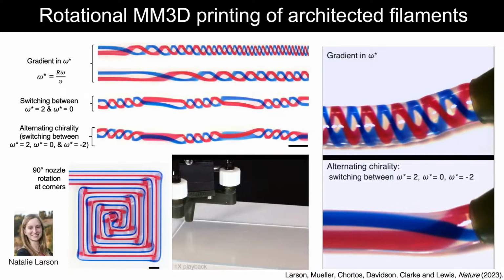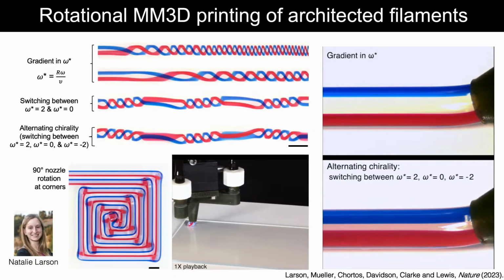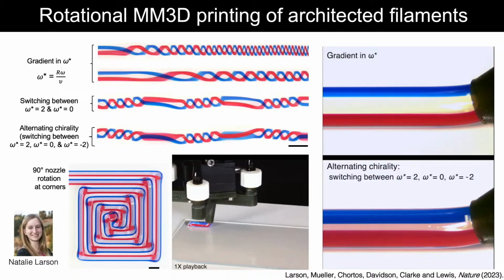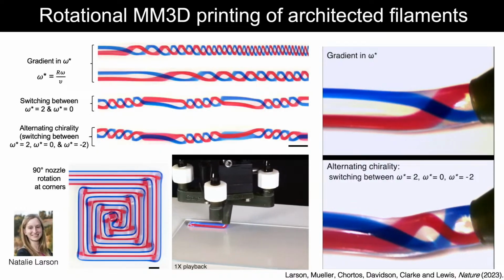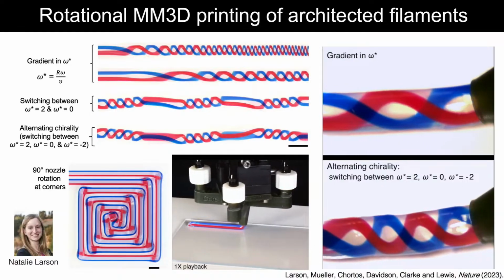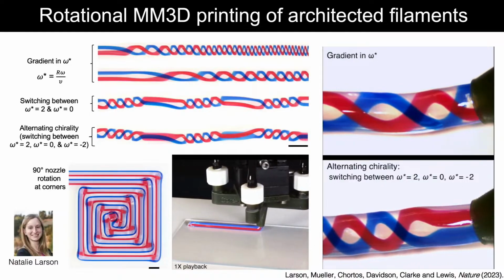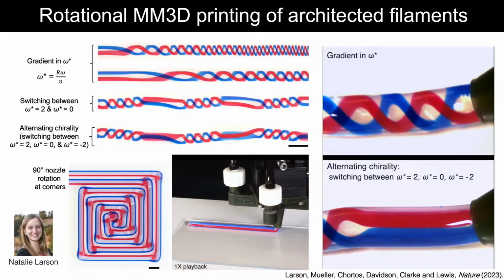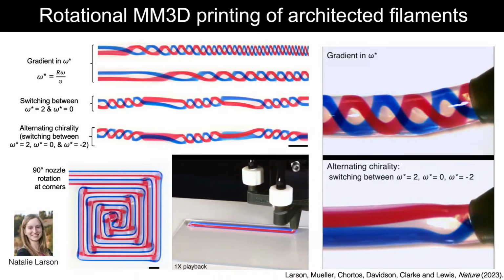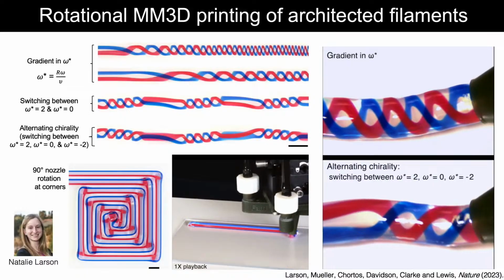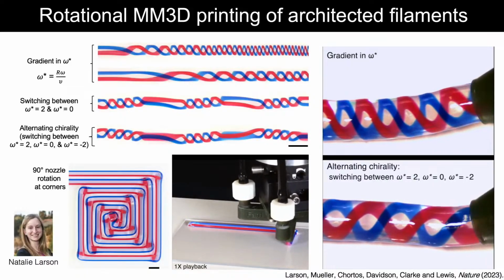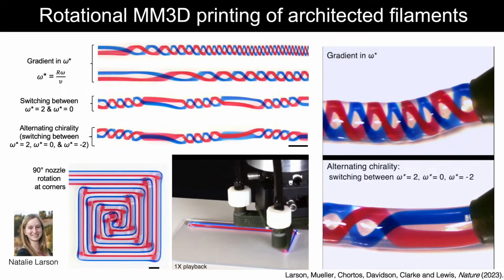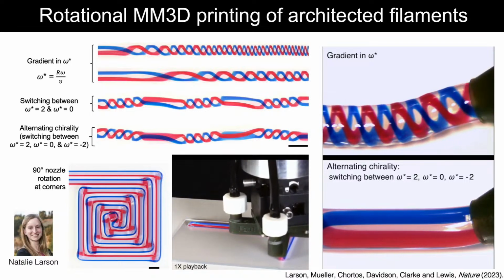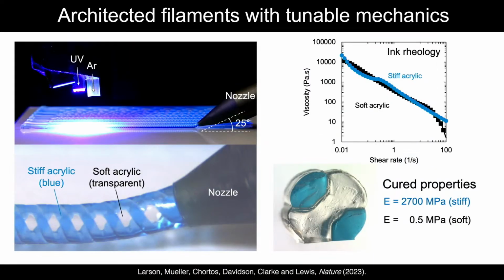And then if we want to create straight channels or straight designs that actually turn at corners, you'll see that this is not rotating at all. And then every time we hit a corner, it rotates in order to keep the blue on the outside and the red on the inside, right? So there's higher degrees of complexity that can be built into these architectures depending on what you're trying to achieve.